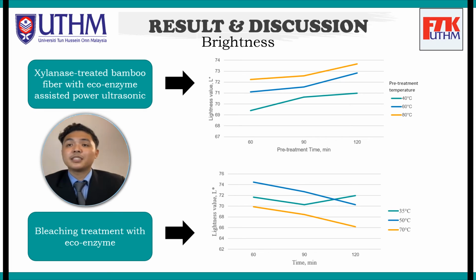Bleaching treatment condition of 50 degrees Celsius and 60 minutes with ECO-ENZYME has the highest brightness value, which is 74.46. The highest brightness value for XYLANASE-treated bamboo fiber with ECO-ENZYME assisted power ultrasonic is 73.66. There is a small difference since the XYLANASE-treated bamboo fiber only uses 80 degrees Celsius, where the optimum temperature for the ECO-ENZYME is 35 until 50 degrees Celsius.